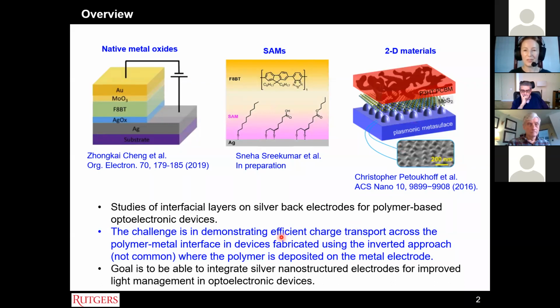And so the challenge we've set ourselves is to demonstrate efficient charge transport across a polymer metal interface in devices fabricated using the inverted approach. And this is important because this is not commonly done. So normally in optoelectronic devices, you build them on an ITO on glass electrode. You start with ITO on glass, that's the transparent electrode. You put usually a hole or electron transport layer, then this organic semiconductor, and then the metal top contact with another interfacial layer in between.